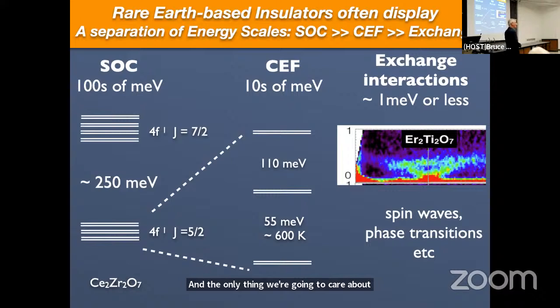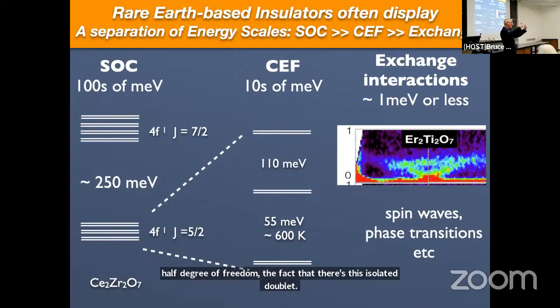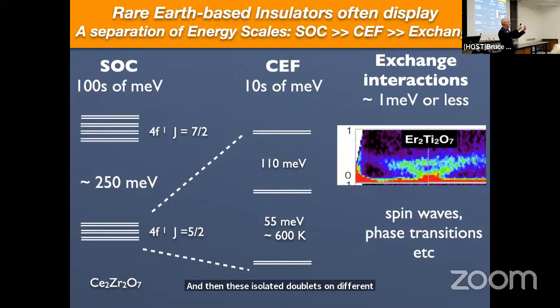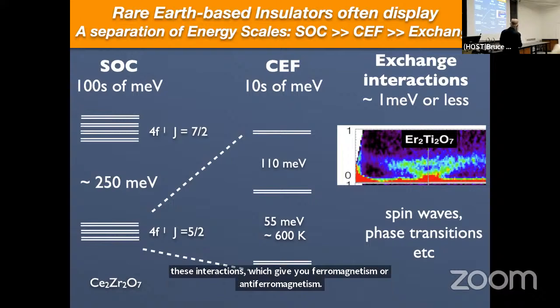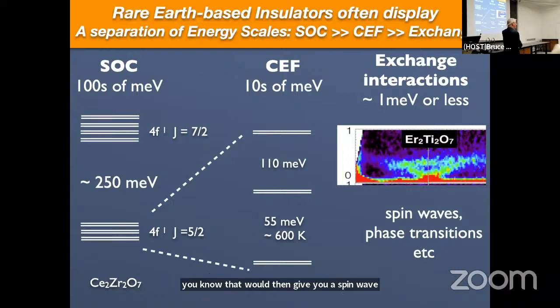And so that's what's going to give us our spin-1/2 degree of freedom, the fact that there's this isolated doublet, okay? And then these isolated doublets on different sites are going to start to interact with each other by these interactions, which give you ferromagnetism or antiferromagnetism. And if this was conventionally ordered, that would then give you a spin wave band with an interaction of about 1 meV. So this is what goes on in all magnetic insulators.